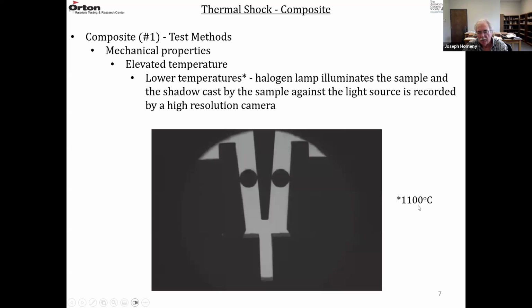So at the lower temperatures, and probably temperatures less than about 1100 degrees C, the halogen lamp illuminates the sample, and the shadow that's cast is recorded by a high resolution camera. So you can see the loading wedge here, the cylinders, the transmission wedges, and then the notch. So as the load is applied, as a function of the load, you can get the displacement, the crack opening displacement.